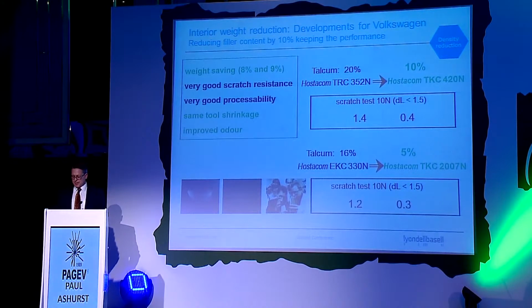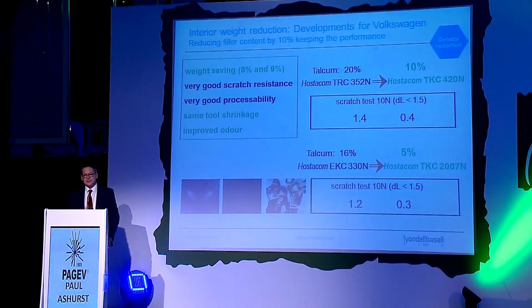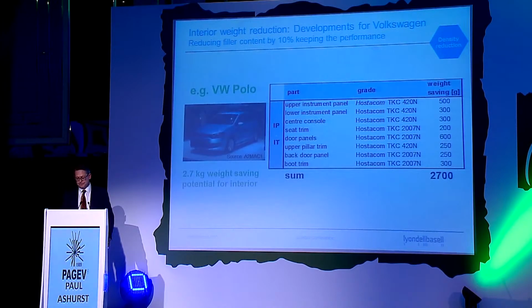And we're able to do this by using higher quality talcs and also our own process technology polymer. And just look at the effect. By moving those two materials to the new materials, on the VW Polo, the weight saving is 2.7 kilos. And if you imagine multiplying that through many parts and many more cars, you can see that a simple density reduction through talc reduction can have a significant effect.